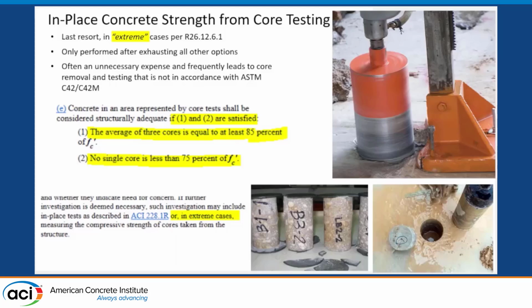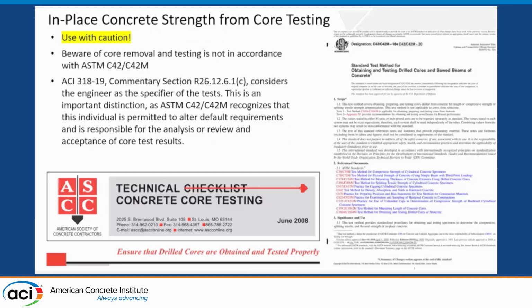So again, sometimes it is found to be a quick slam dunk, and other times, and quite often other times, it can just cause more confusion and more hand-wringing by the parties. So I guess my comment to all is basically use with caution. Beware of core removal and testing that is not in accordance with the ASTM C42. A lot of the low values that come out of coring arguably come out of not strictly following the ASTM